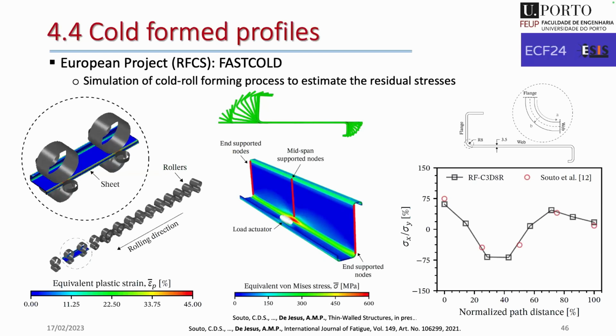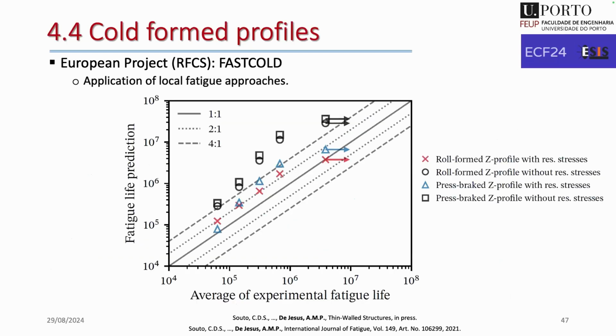So in this case, we solve by modeling the process of the profiles' production in order to get the profile of residual stresses. And in that way, we are jumping to what we call an acceptable accuracy band for the predictions. These red crosses were considering the residual stresses from roll forming. If we adopt, for example, residual stresses from press brake profiles, which is not exactly our process, it will not work as nicely as we should expect.